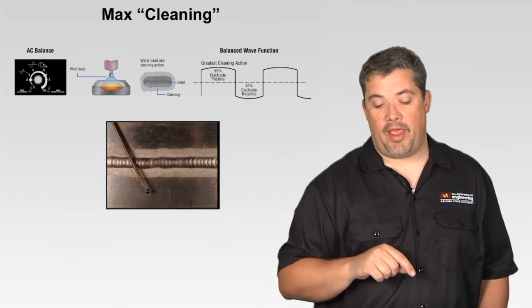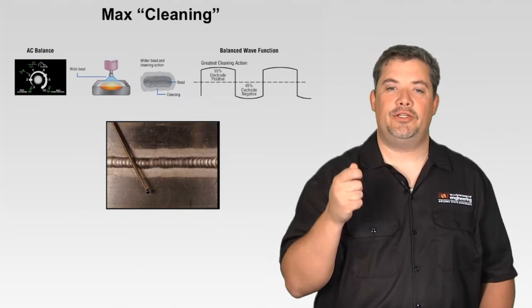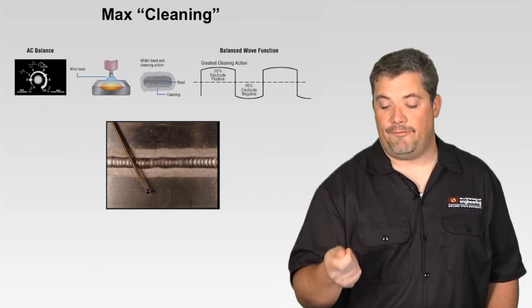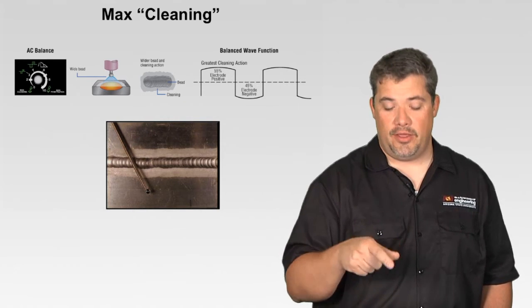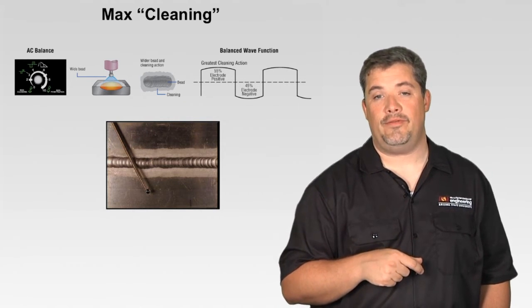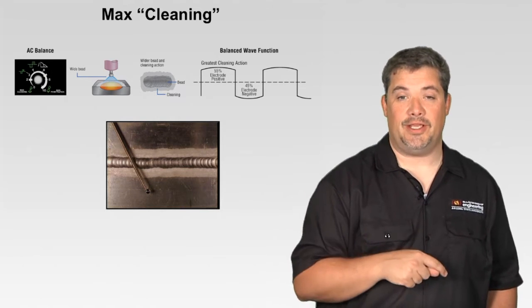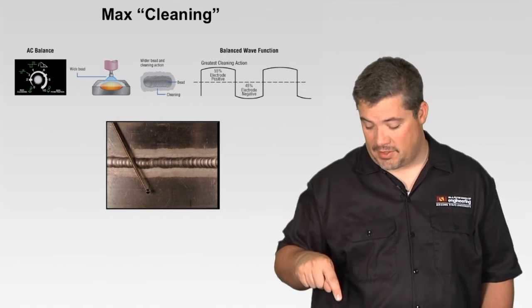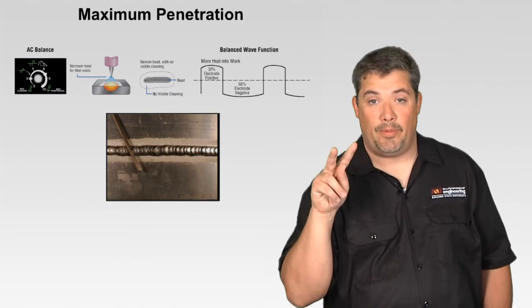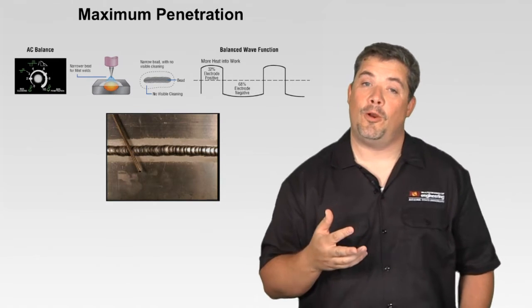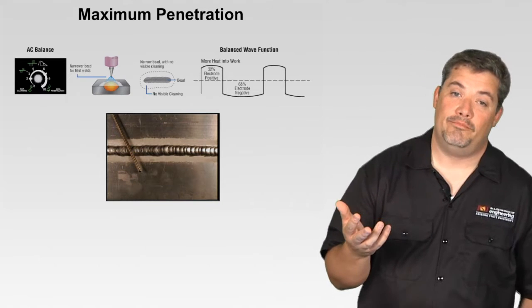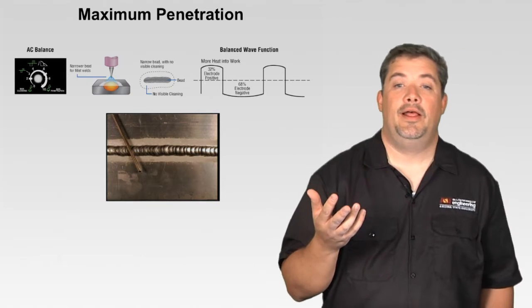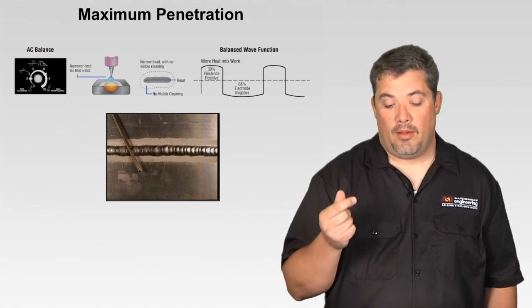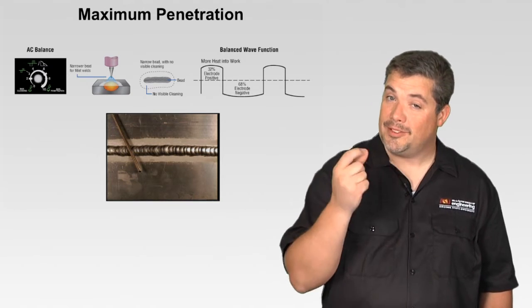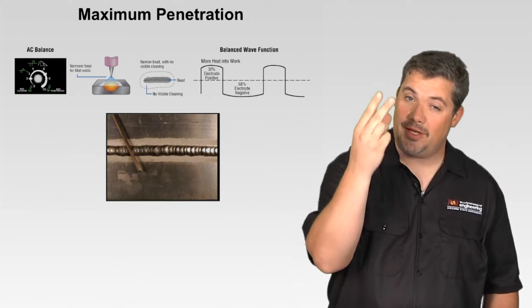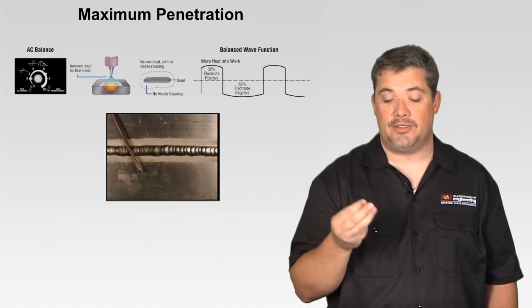But this is where I now have what we represent as percentage electrode negative. Here I had 45% electrode negative. You can see the ball on the tungsten is bigger than the previous slide, and the white etching is even more predominant than the previous slide. Then on the maximum penetration setting, penetration is a poor word. It should just say percentage electrode negative. It should be the general name here. It's not controlling how much penetration into the part, because penetration is a function of volts times amps times time. Can't repeat that enough.